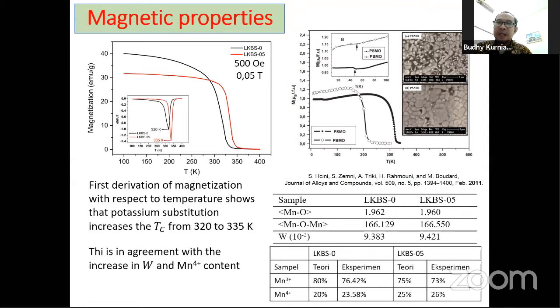So from the M-T curve, what we find from this experimental result, first, we find the Curie temperature. We can get the Curie temperature from the first derivative of magnetization with respect to temperature. From the inset of the figure, the Curie temperature is about 320 K for the 0 potassium and 335 Kelvin for the 0.05 potassium doping. So the doping of K will increase the TC of the sample.